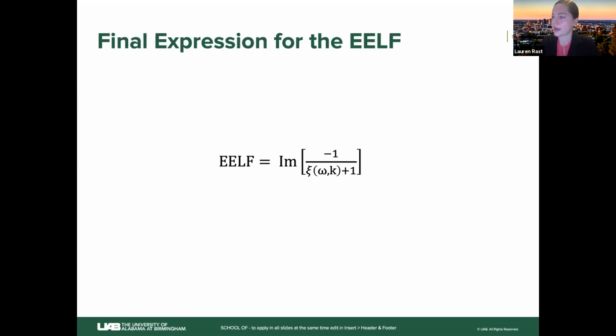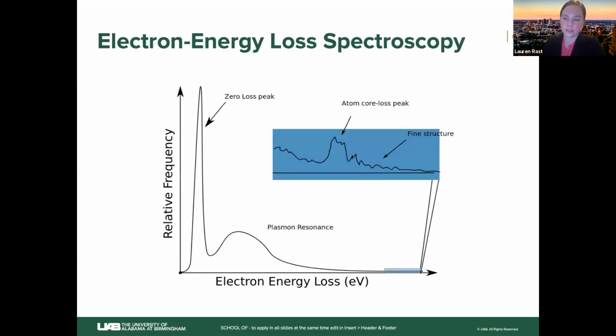Once the individual dielectric functions were obtained from the calculations, we combined that with the empirical data and put this into the composite dielectric function and then calculated the spectra. So I'll show you the model spectra here.